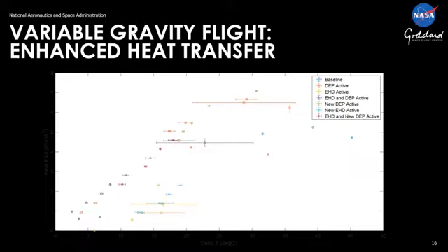So this is just raw EHD data. I apologize for the background. This is nothing more than applied heat on the y-axis and delta T on the x-axis. So what this chart shows is that you have the baseline heat transfer, which is the light blue, and that tends to be on the right-hand side. This is data that we took in the lab. And then what you see is we have data with the DEP active, and then the EHD active, and as you activate the EHD components, you move to the left, which means the heat transfer improves as you go along. The big jump you get is with the DEP as opposed to just increasing the flow rate on the liquid pump, the coolant pump. Next chart, Sean, please.